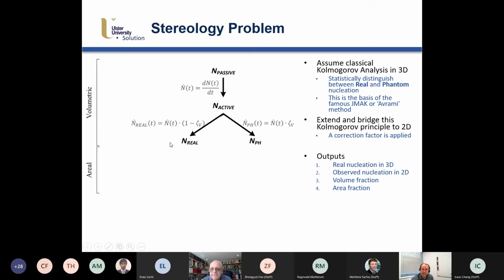So you have real nucleation. These are the ones that we're trying to capture that really nucleate in 3D. But extending that principle again to 2D, we can look at Kolmogorov principles here. So we can get the real nucleation events, and we can calculate how many of those are observable based on area fraction and volume fraction and the depth of the sample. Or we could just go directly from the activation rate and calculate the number of observations based on this. So it gives you the same results, whichever way you do it. That's the one feature.